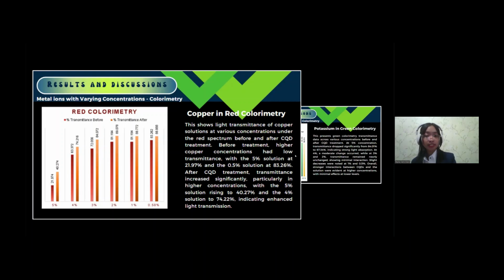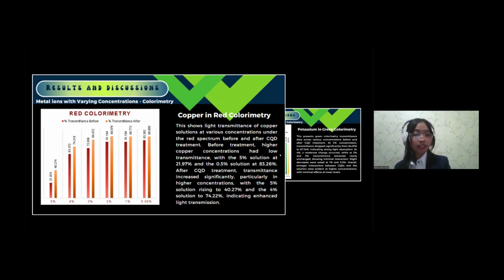through over 83%. After treatment with the CQDs, more red light got through, especially in the stronger solutions, like the 5% one jumping up to about 40% transmittance. This means that the CQDs help reduce copper's light absorption, especially at higher concentrations.